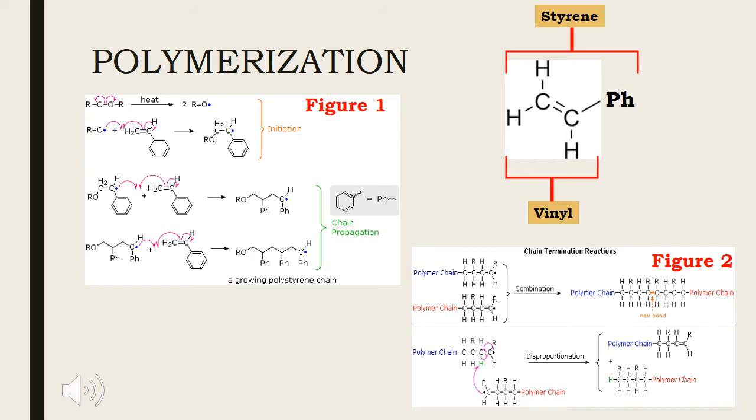Note that in both types of termination, two reactive radical sites are removed simultaneously, being converted into stable products. Since the concentration of radical species in a polymerization reaction is very small relative to other reactants, for example monomers, solvents, and terminated chains, the rate at which these radical termination reactions occur is very small, and most growing chains achieve moderate length before termination.